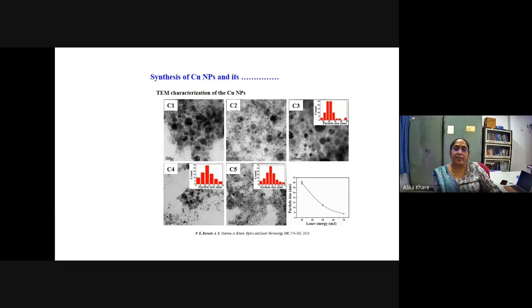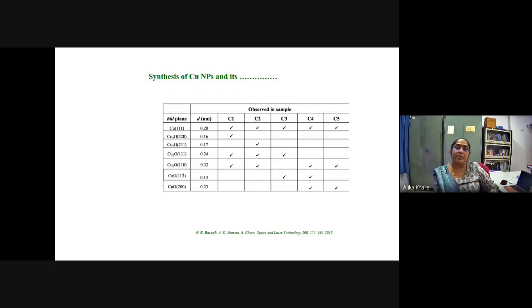Here is the particle size analysis, and these are the TEM images for all 5 conditions. Here we show the particle size as a function of laser energy, so by changing the laser energy one can control the size of the nanoparticles. This table lists the various phases formed under the various conditions.